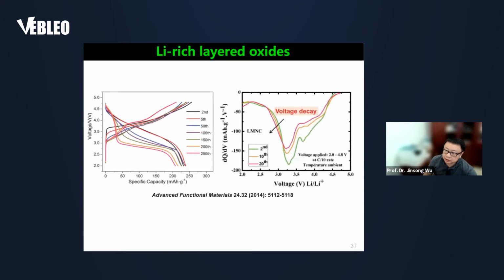So why do we need the lithium-rich electrode? It is because we want to have high capacity. But actually there are many problems related to lithium-rich layered oxides when they are used as cathodes. The first one is that they are unstable. The capacity is lost; it becomes smaller and smaller with cycling. The second problem is the voltage decay. The voltage decreases with cycling. So there are several problems, and those are the big ones.